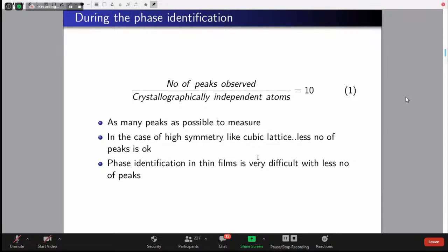But usually when we go for simple cubic materials, that many peaks will not be available in the measurement range, the 2 theta range. So in those cases, we can accept fewer. But for low symmetry, which means after hexagonal, such as tetragonal, triclinic, rhombohedral phases, we should be able to measure a large number of peaks. This is very essential. With one single peak, nobody should identify whether the phase is cubic or hexagonal.